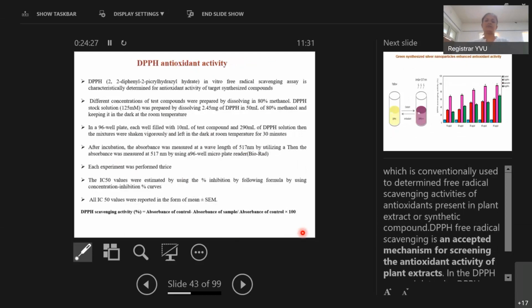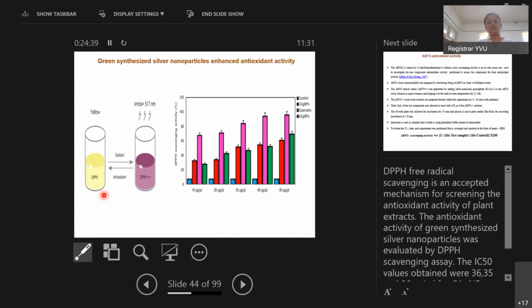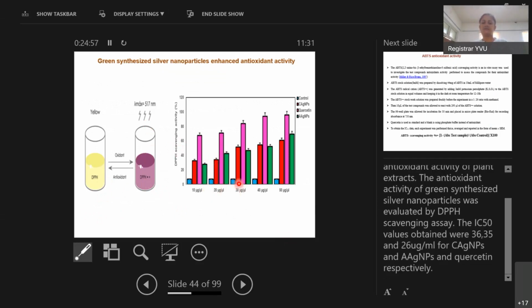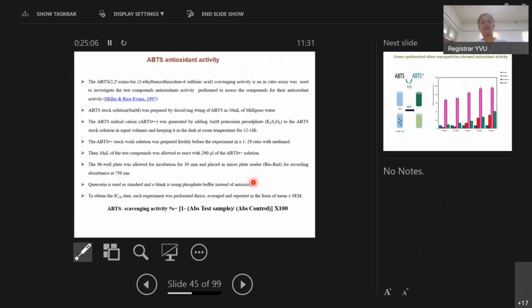After that, I investigated the antioxidant activity of green synthesized silver nanoparticles. I used the DPPH antioxidant assay. This is the protocol I have used. The purple color solution turns into a yellow color solution, measured at 517 nm. This is the graphical representation of antioxidant activity. The IC50 values obtained from Catharanthus roseus silver nanoparticles were 36 ug/ml and 35 ug/ml, and quercetin as standard was 26 ug/ml. After that, for ABTS antioxidant activity, I used the Miller and Rice Evans technique.